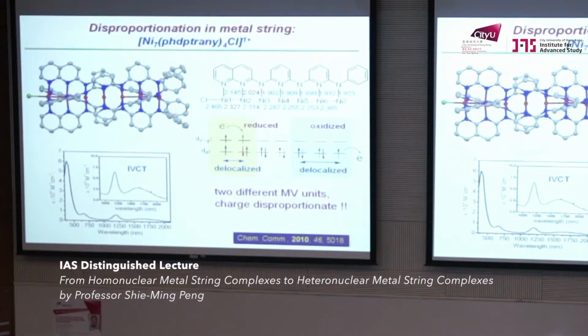And also many interesting properties. The ligand can be hybridized between naphthyridyl and pyridyl. So this one has the naphthyridine on one side and amido group on the other side. So that means this side is more anionic, this side is more neutral, and because of this phenyl group, we use stereochemical control and can get the 4,0 isomer. Although it's unsymmetrical, I can force this 4-phenyl group onto only one side. So this unsymmetrical coordination geometry will stabilize nickel 1, nickel 2.